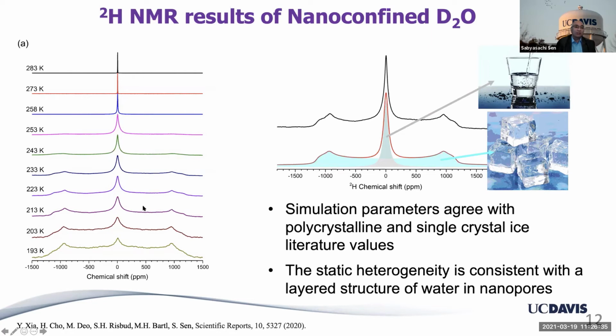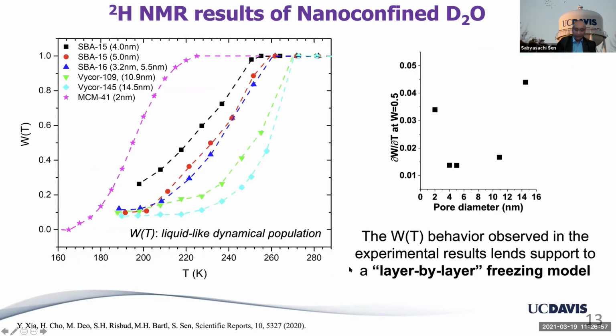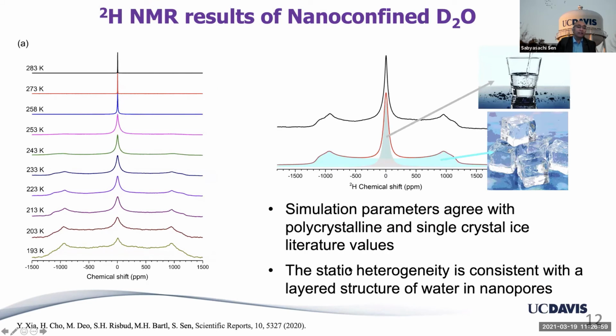So this liquid-solid coexistence or water-ice coexistence seems to be very, very stable, with a specific ratio as a function of temperature. This indicates that there is a static heterogeneity inside the nanopore and presumably a layered structure, because as you cool, different layers of water freeze and the rest of it stays liquid, and then it progresses, some more freezes, and this solid-like signal increases in fraction with respect to the liquid-like signal.